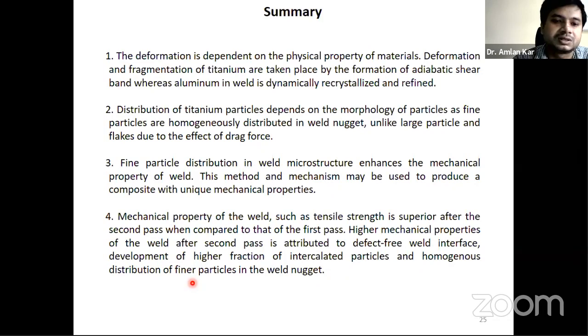band formation. And because of the adiabatic shear band formation, we get different kinds of finer particles, and this particle fraction is very important, because if you deform the material further, we can get even finer particles. Okay, and this is a continuous process, and because of that, we can tailor the microstructure in the weld nugget in the case of welding, and we get very good mechanical properties of the defect-free welds.